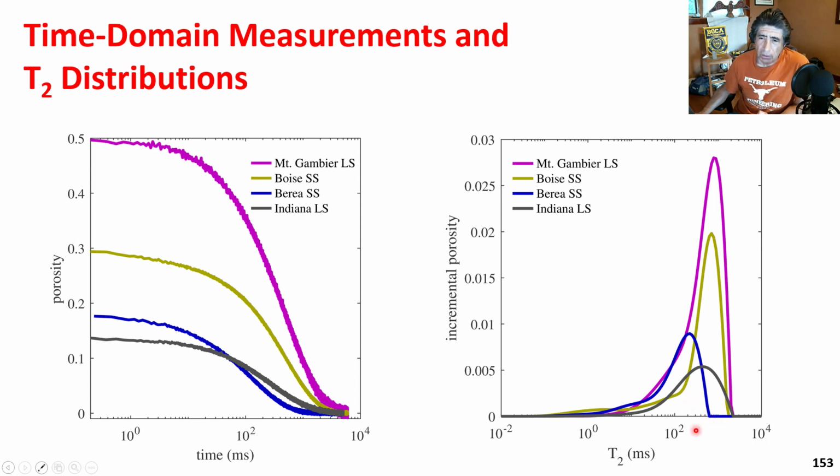Then, second, we are going to look at the distributions, and we look at the dominant pulse, or the dominant contribution. It's almost like you're trying to find what is the dominant time. Sometimes we have bimodality, sometimes you have unimodality, sometimes you have skewed distributions. When you have a symmetric distribution, that means that you have a single exponential. But when you begin to have a distribution that is skewed, then that means that you are summing more than one dominant time pulse. And then we have to interpret that in a different way.